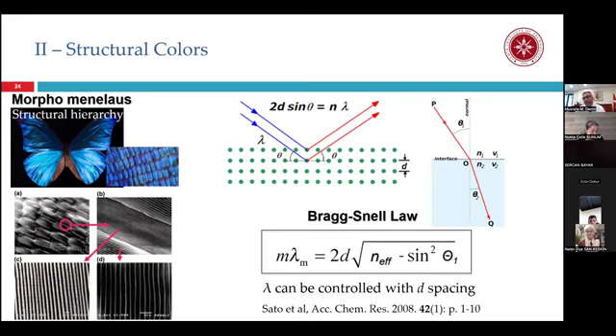On the left-hand side of this equation, you have m, which is an integer, and lambda is the wavelength. We are in visible light, and wavelength means color. On the right-hand side, you see a complex root, and you have d, the d spacing or periodicity, like the interatomic distance. As you see, lambda, the color, is proportional to the distance of the periodicity. We perceive only a very limited range of wavelengths, from 400 nanometers to 800 nanometers. So if we apply these boundary conditions, d should be between 150 and 300 nanometers. That means if you are able to fabricate a material with a periodicity of 150 to 300 nanometers on the surface, you can give color without any pigment.